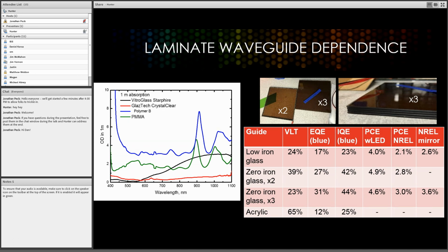If you divide by the absorption spectrum, you get the IQE, and this is telling you how close to your potential you are. And we're approaching 50% for the best case. So essentially half of all the photons absorbed are being re-emitted at the edge. And the intrinsic limit for this material, if you don't do any tricks with total internal reflection, is around 70%. That's just because there's an escape cone of light that can get out if it's emitted too close to normal incidence.